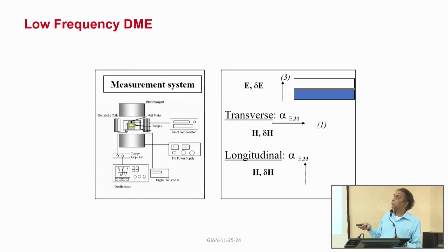And here is a simple setup to measure the direct magnetoelectric effect, that is, the influence of a magnetic field on the ferroelectric phase. What you need is to apply, for the voltage coefficient, a bias magnetic field and an AC magnetic field. You can apply a bias magnetic field with a solenoid, an electromagnet, or a permanent magnet. With a permanent magnet, the field is constant, but if you want to measure it as a function of bias magnetic field, then you must use an electromagnet or a solenoid. The AC magnetic field can be produced by a pair of Helmholtz coils.